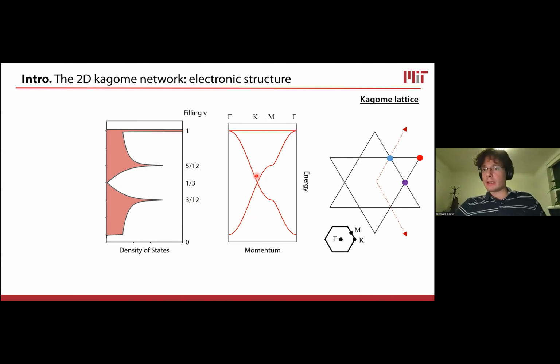And so you have the Dirac fermions at the K point, you have the Van Hove singularities at the M point, so you have vanishing density of states at the Dirac point, and then an enhanced density of states at the Van Hove singularity because you have this saddle point dispersion where there is a pileup of density of states. And in addition to the bands that are known from other systems like graphene, you also have this flat band, which arises because of the very peculiar hopping pathways that exist on the Kagome lattice. I will not discuss that in detail, but it's a really beautiful phenomenon that is peculiar to the Kagome lattice and occurs because there is essentially a mechanism of destructive interference in the hopping pathways that involve electrons that are trying to delocalize themselves in the lattice.